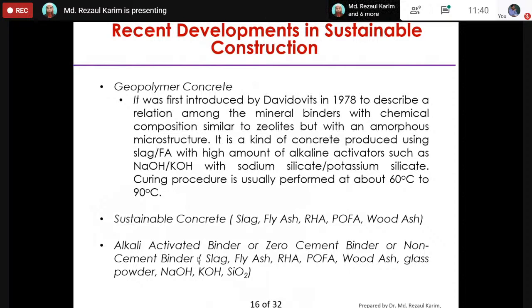Another development is sustainable concrete: concrete containing slag, fly ash, rice husk ash, palm oil fuel ash, wood ash, and so on. All of these materials can be used in concrete as a supplement of cement as well as a supplement of fine aggregate, and that reduces the cost of the concrete, which we have already discussed in the earlier slides. Some recent developments are alkali activated binder or zero cement binder, non-cement binder. In fact, I did my PhD research on the development of zero cement binder. I produced a non-cement binder using slag, fly ash, and rice husk ash, and another composition also of slag, palm oil fuel ash, and rice husk ash with chemical activator. I used sodium hydroxide, potassium hydroxide, and calcium hydroxide for production of the zero cement binder.